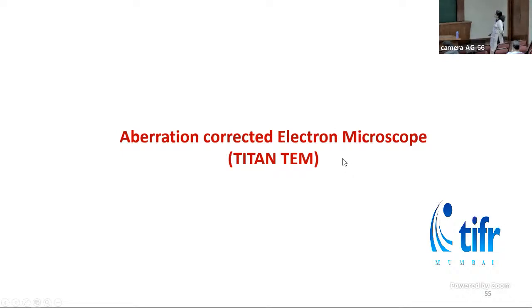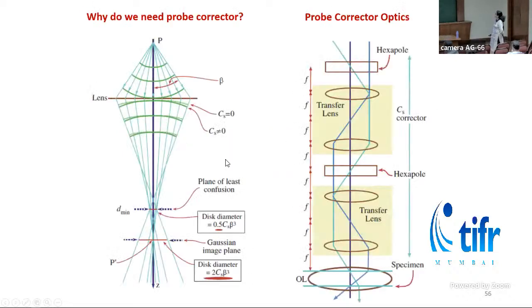I'll come to the aberration corrected electron microscope, Titan. Now, why do we need a probe corrector? If you remember, I mentioned to you that if we use a 200 kV electron beam, we should get a resolution of 0.0015 nanometer. But do we get that? No, because the electromagnetic lenses are not perfect. And instead of forming a spot, they form a disk. That's why we are not able to image to that resolution.